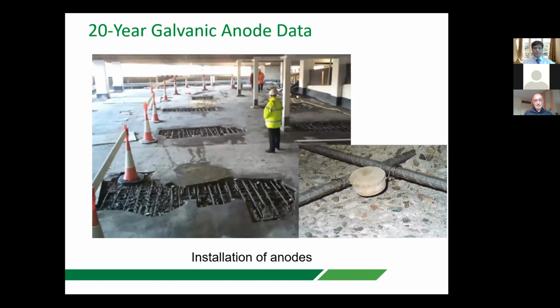And we came up with the solution. First of all, we tried to understand the issue, and what was actually happening was when you carry out a patch repair, you have now forced the steel within the patch repair to become the cathode, being the area that's non-corroding, but drives the anode, being the area that is corroding. So initially, what was within the patch was the anode, and therefore the corroding region. So steel was corroding. We now fixed that. We forced it to become a cathode, I beg your pardon, which means that any slight contamination of the periphery, of chlorides perhaps, or carbonation, or a change in pH in the concrete, would force the surrounding steel to become anodic and therefore start to corrode. And that was basically the principle.